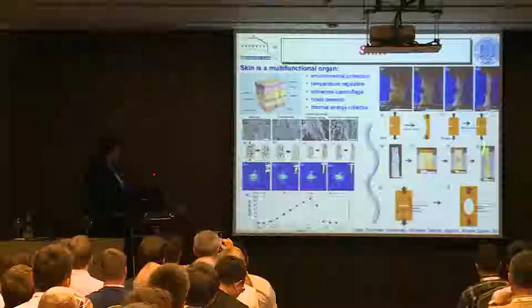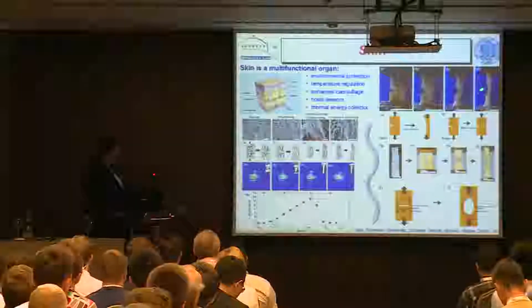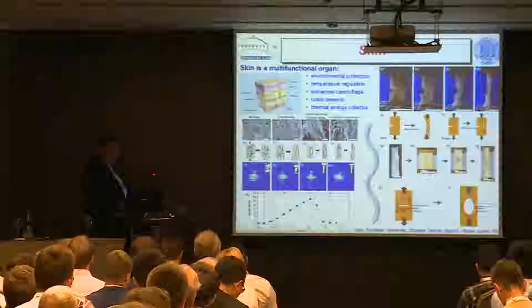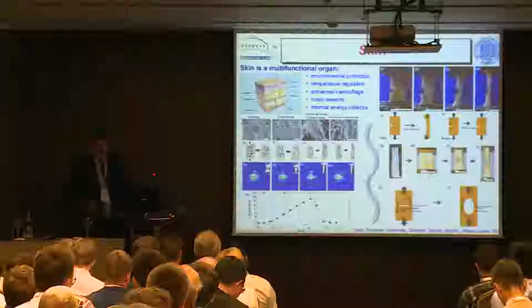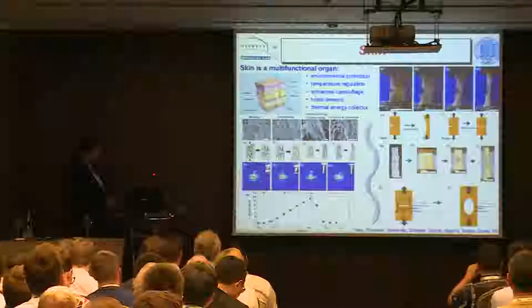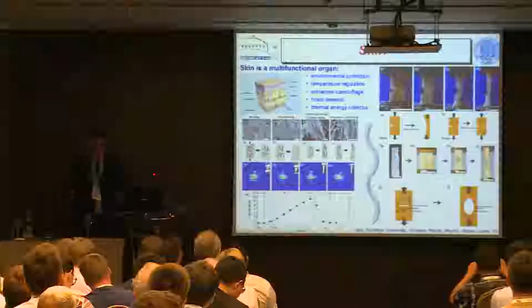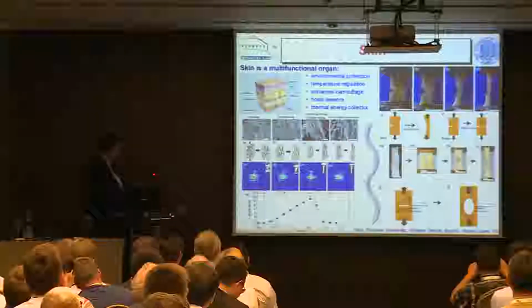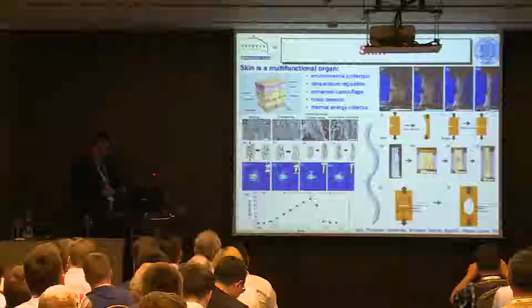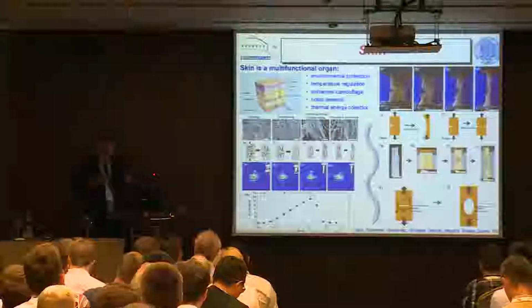So skin is a pretty complicated material, but you can see with these sort of pictures here how, as I said, it's almost impossible to break. Whether you have an internal or an edge crack, it just doesn't break. So why is that? Well, if you look into the many layers in skin, the dermis layer consists of these collagen fibrils. Now, they don't have mineral, they're generally just pure collagen, but they're long and they're twisted and they're curved. And when you pull skin, we put this in the synchrotron and we can watch the movement of the collagen under load.